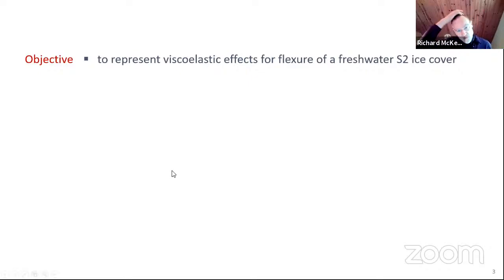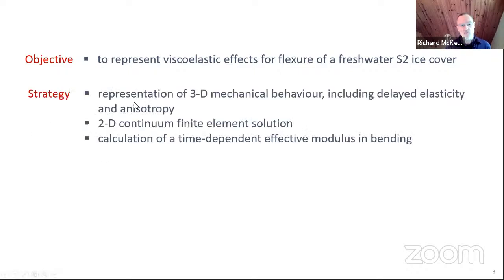What we've tried to do is represent viscoelasticity. In this paper, we deal with freshwater ice, but the techniques are applicable to sea ice as well. The approach we've taken is a representation of 3D mechanical behavior, including delayed elasticity, accounting for example for isotropy in the horizontal plane for S2 ice because of randomly oriented crystals, and also anisotropic effects. We could deal with a fully 3D anisotropic medium. We've implemented this in a 2D finite element solution, and we calculate time-dependent effective modulus in bending.